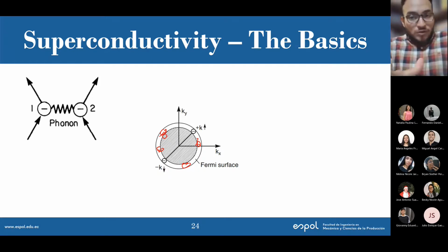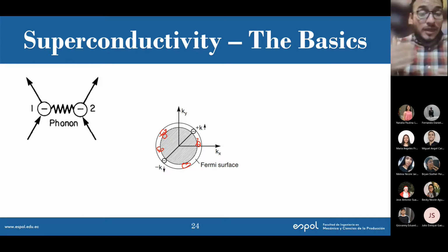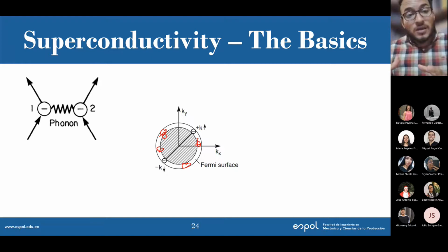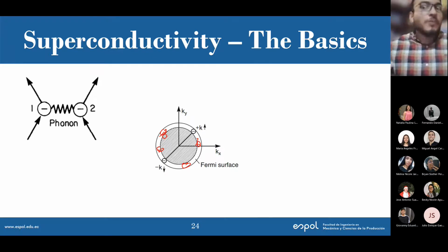So this theory explains very nicely what happens with superconductivity in metals, because it explains what happens at low temperature, when I have the superconducting state, and what happens at high temperatures when I lose that superconducting state. And I lose it because I no longer form these Cooper pairs; this interaction between phonons and electrons is not forming Cooper pairs anymore. What's happening is a scattering of electrons, and therefore I have a normal state.